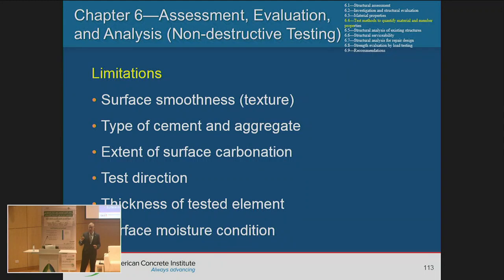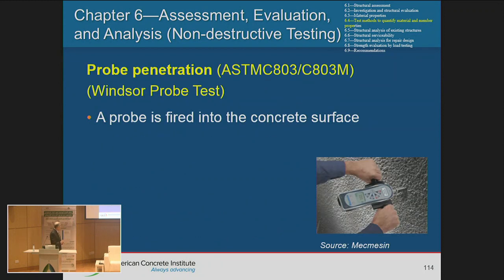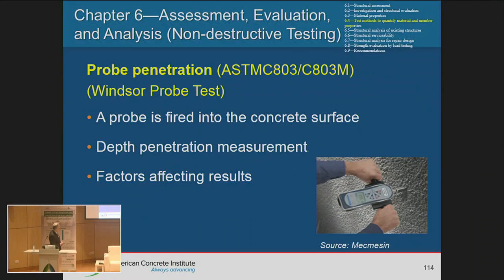Although the manufacturer may give you a calibration telling you that if you hit that rebound number, then that's your concrete strength, it's not acceptable because there's a lot of variability with that instrument. The other one is the Windsor Probe. That one is more accurate, more reliable. You have a pin that you shoot into the concrete to penetrate it, and based on that penetration, it will give you the concrete strength.